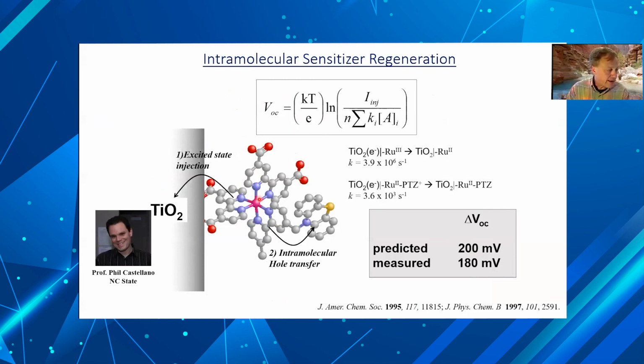Phil Castellano, who back in regenerative solar cells days looked, he's now on the faculty at NC State, looked at a single methylene carbon and hole transfer out to this. And we found in this case that there was a real advantage to moving the oxidizing equivalent out here. You could generate a larger open circuit voltage, get more Gibbs free energy from the solar cells.